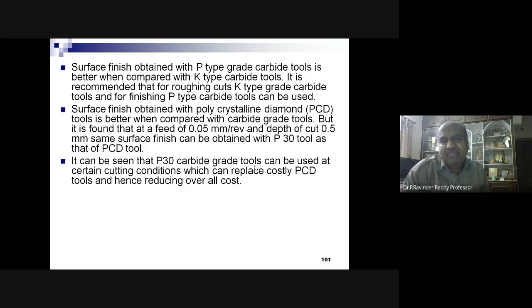Surface finish obtained with the P-type grade carbide tools is better when compared with K-type carbide tools. It is recommended that for roughing cuts, K-type grade tools, and for finishing, P-type carbide tools can be adopted. Surface finish obtained with polycrystalline diamond tools is better when compared with carbide grade tools, but it is found that